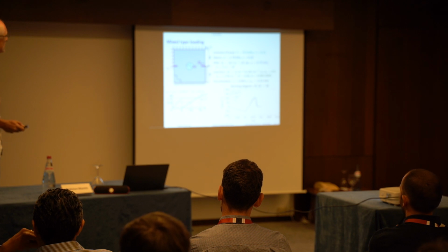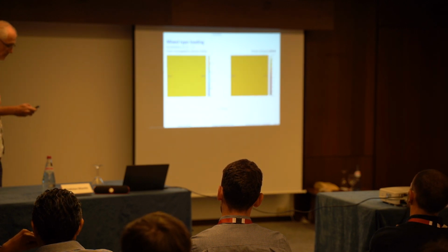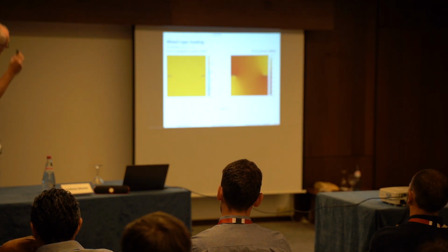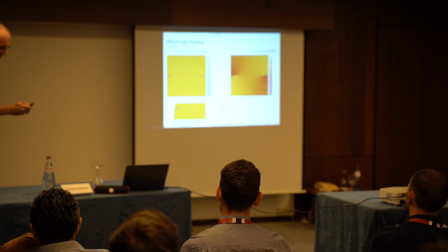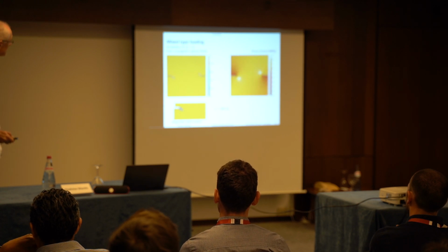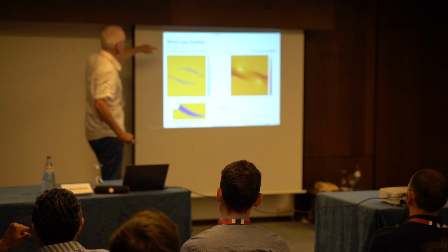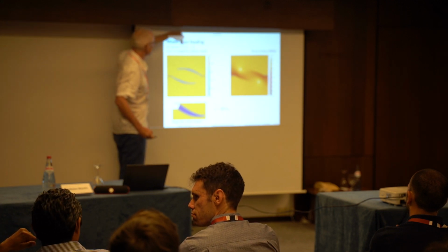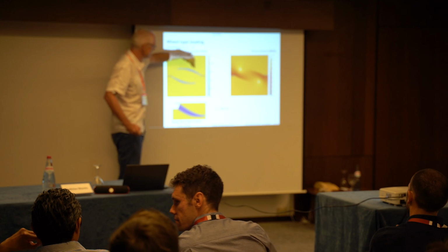Finally, the same comparison for this curved interface, which represents the inclusion. What about the results again? On this slow computer, we see some concentrations, and now the crack starts to appear. This is for the case when we have a large ratio between GC2 and GC1.